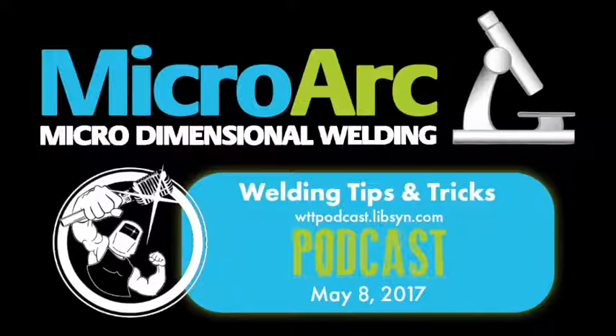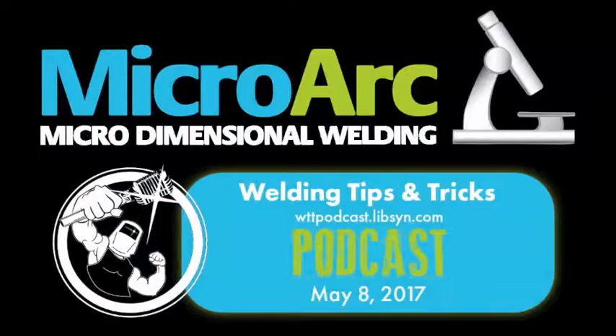If it's a shut-off area, or a gate where the plastic runs through, they might want something where we'll use an H13 or an H12 that has a lot of tungsten in it, for wear resistance for a gate. A gate is where the plastic comes through to fill the cavity. So we mix and match alloys all the time depending on where the weld is being applied to the part. If it's a shut-off area, a gate, an inside corner, or an area where it doesn't matter what Rockwell it is because it's just a molding surface. So we constantly are mixing and matching alloys.